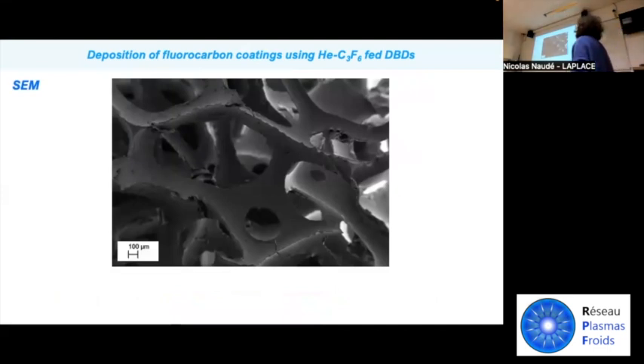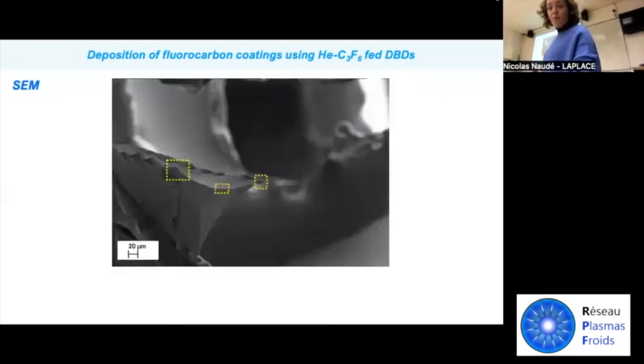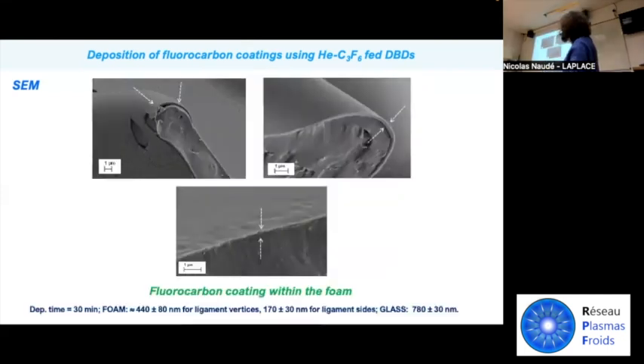Let me show some images from SEM analysis. First of all, the low magnification image shows that plasma ignition does not alter the morphology of the polymeric porous material. And in other investigations, we also confirmed by mechanical characterization that the mechanical properties did not change after plasma treatment. But if we look at a cross-sectional ligament and at some parts of different regions of the ligament, we can really observe the presence of a thin layer within the foam.